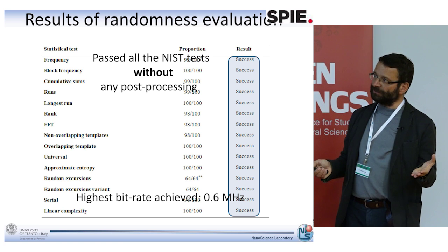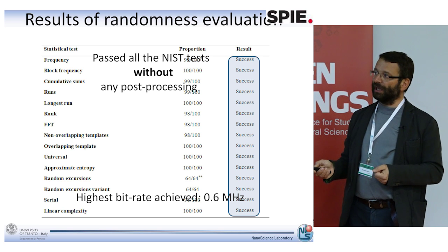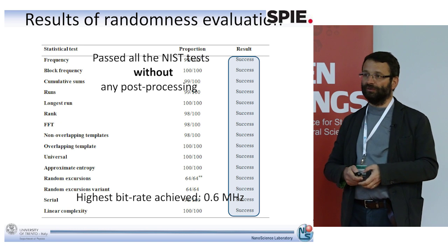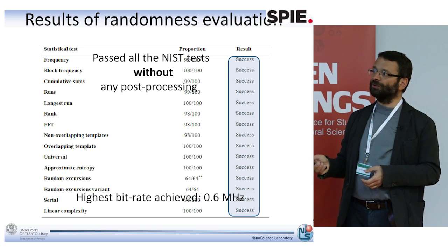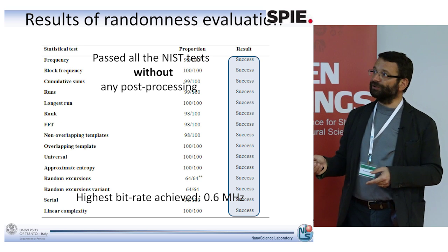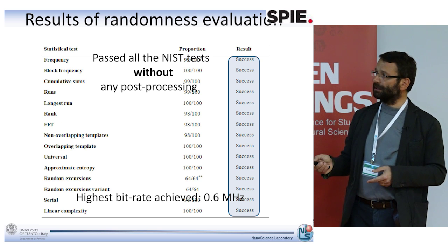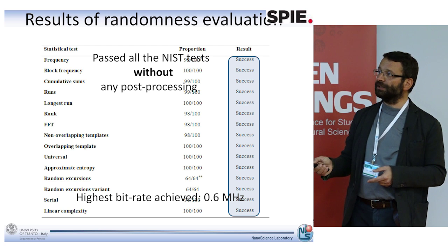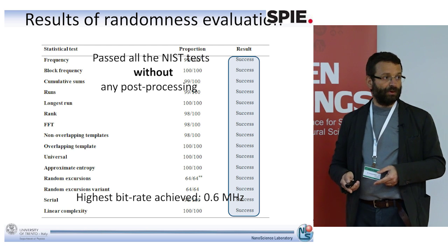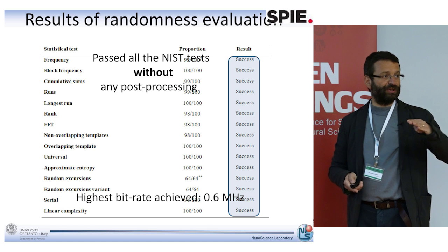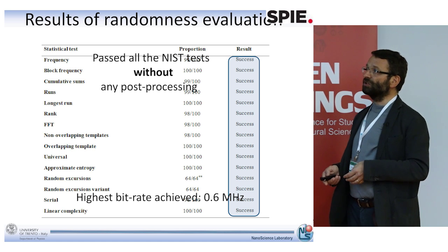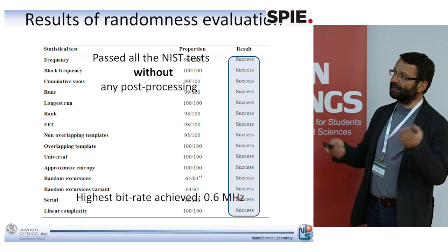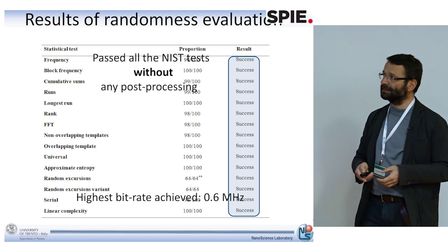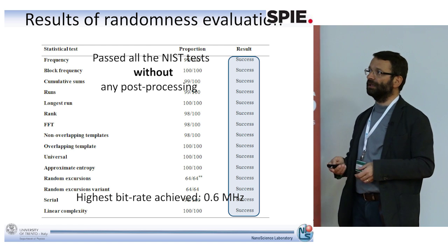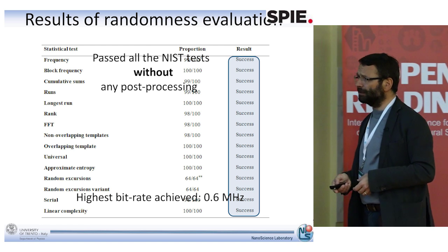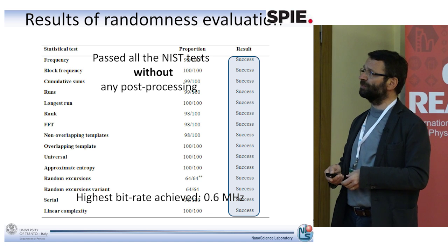So these are the random numbers that are generated. And so we can have the arrival or not the arrival of the photon. And so this is the probability to get 0 or 1. And what you see here is that as a function of time, this probability is 50%. Okay? So very good random numbers generated without any post-processing. So we look at several tests that are available. So all the tests pass. And so we get these tests passed without any post-processing.